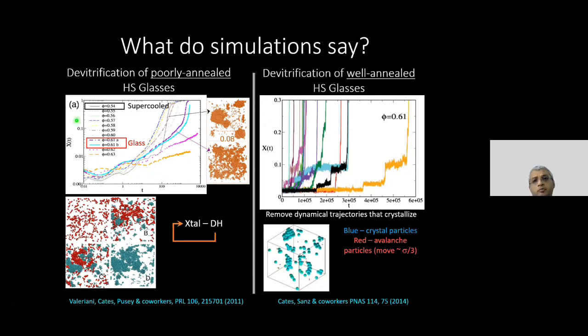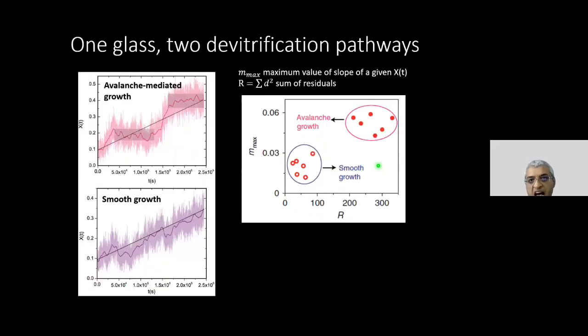So in simulations, you have to follow two different protocols to see the two different routes of crystallization, whereas in our experiments, you have a single glass sample and we were observing both the pathways. And now, from this sort of crystallinity profile, you can find out, by fitting a line and looking at deviation from a straight line, whether it is an avalanche mediated growth process or a smooth growth process.